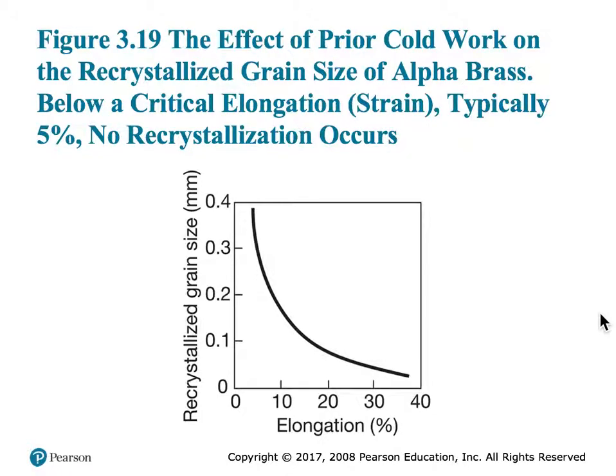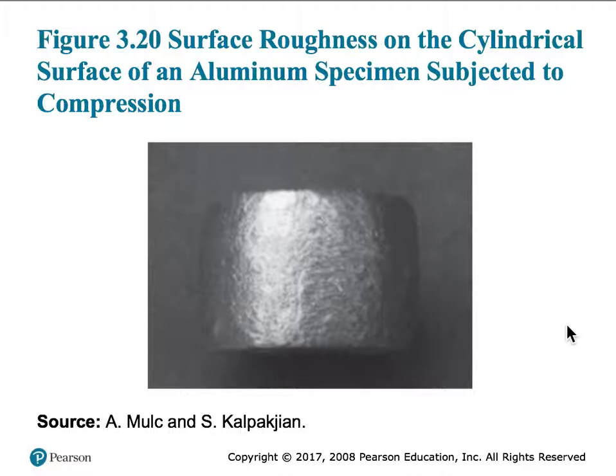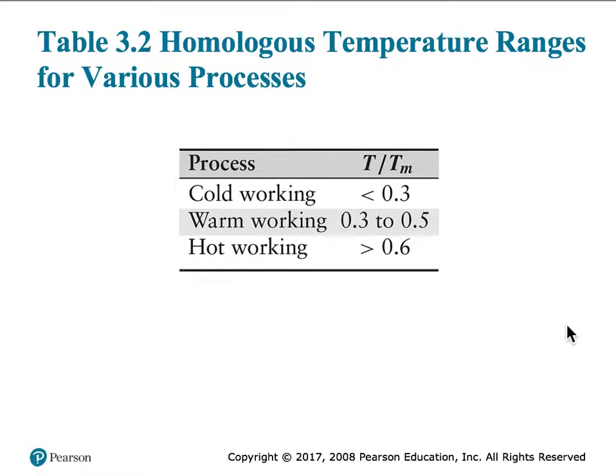In the case of alpha brass, it is 5%. If you look at the handbook, they have done a lot of studies where they have looked at the critical elongation that is required in order to make the recrystallization process go. You may also find that certain deformation processes can lead to some amount of surface roughness on the sample surfaces when exposed to some kind of compressive forces. For example, you see here the surface roughness on the cylindrical surface of an aluminum sample exposed to compression.